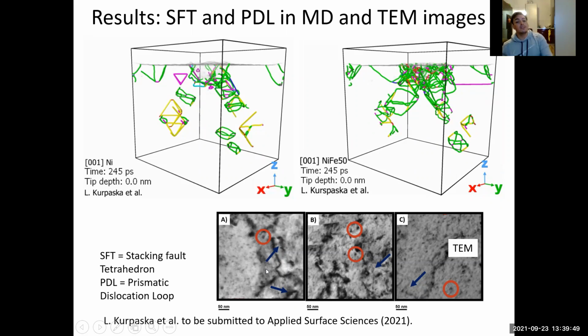So all of them coexist in the same plastic region. Yeah, in good agreement with the MD simulations, all of them coexist in the plastic region because it's an FCC and because of the crystal orientation. But what about when you add 50% of iron? Well, then the story changes, and here, to me, this is another stacking fault, but maybe we need to discuss it a little bit more. But here you have another one. This is for nickel-iron 50%, and then you have more dislocation loops here. But with this TEM image, you don't have too many prismatic dislocation loops. So again, this is a qualitative good agreement between the MD simulations and the experiments.